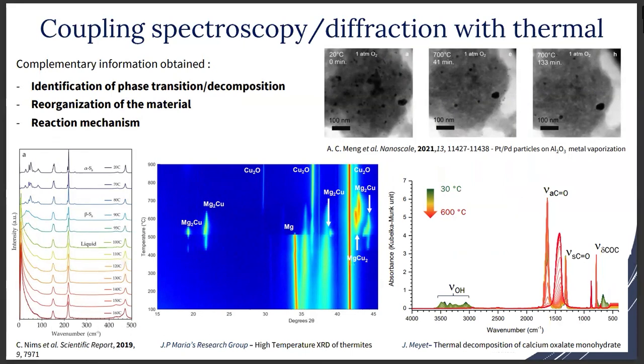On the bottom left, we see an example of non-ambient Raman spectroscopy looking at the phase transition of sulfur as a function of temperature. At room temperature, we have the alpha phase that transforms to the beta phase at 90 Celsius and goes to liquid at 100 Celsius. In the middle is an example of non-ambient XRD experiment of thermite, showing the change of phase as a function of temperature. On the bottom right is the example of the decomposition of calcium oxalate monohydrate as a function of temperature.